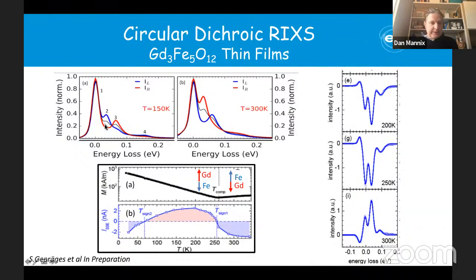You can see this is the first magnon mode below the compensation temperature, and this is the same mode above. The switching that goes on above and below that temperature is very similar to what we've measured with neutrons. So it might be that this is a methodology of also probing the magnon chirality in these materials in a way that is complementary to what we've done with the neutrons.